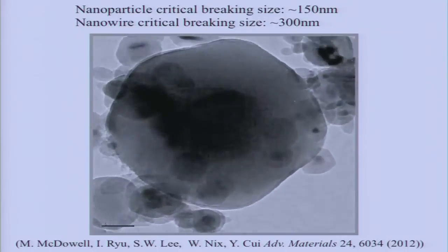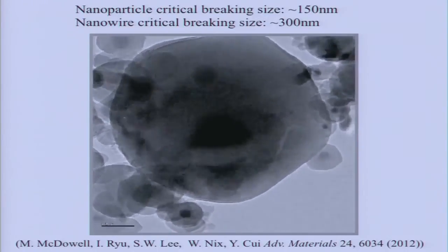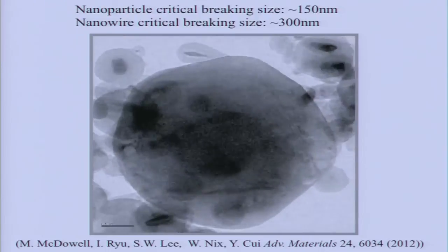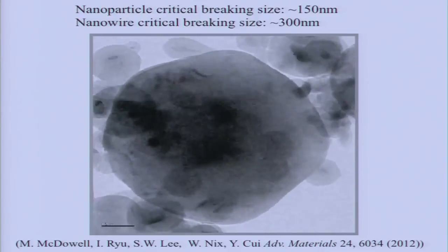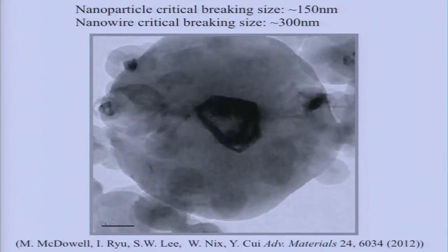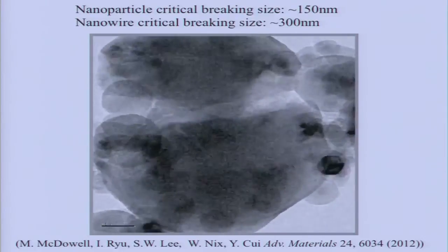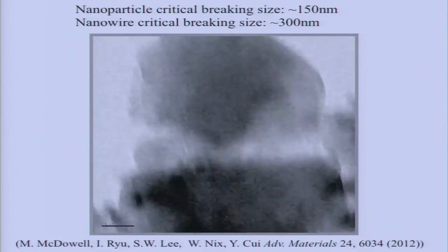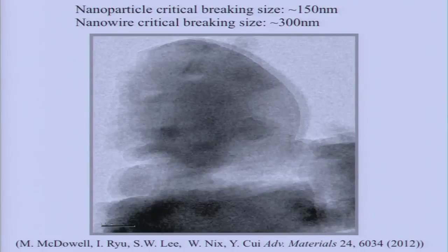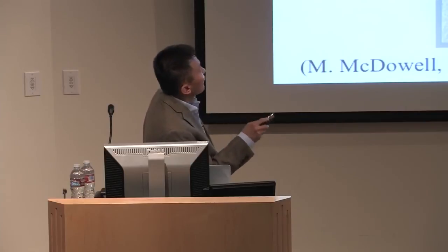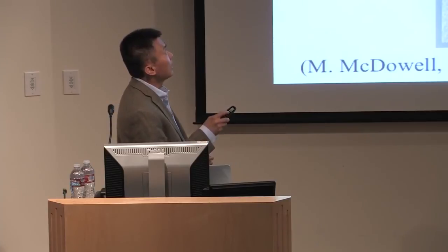It's very hard for silicon to expand towards the outside. The outside shell constrains the inside. At some point, the silicon particle cannot take this stress and strain anymore. It starts to break. This is the failure mechanism, one of the major failure mechanisms. The battery will die. So we also use a technique like this, combined with other techniques like SEM, to identify the critical breaking size.